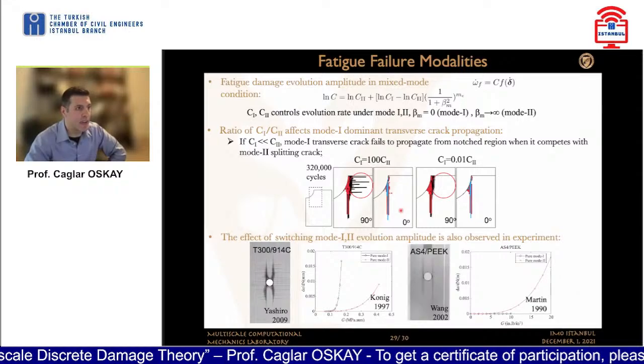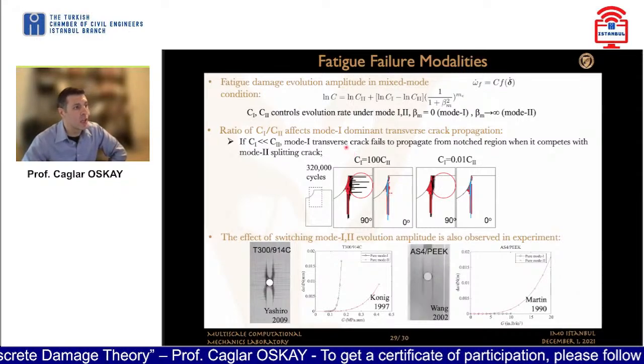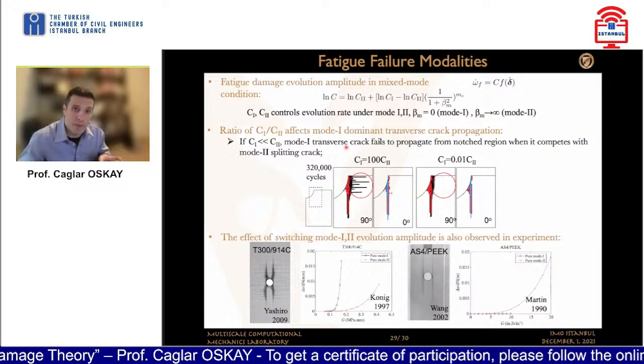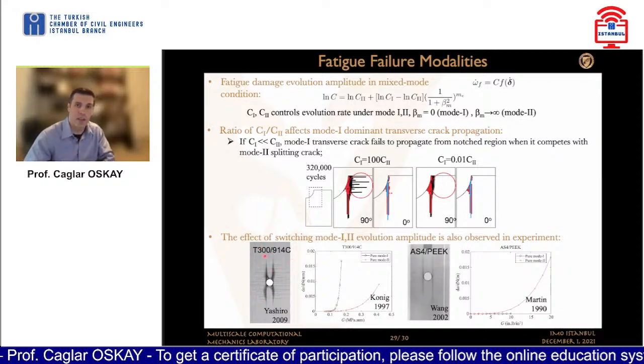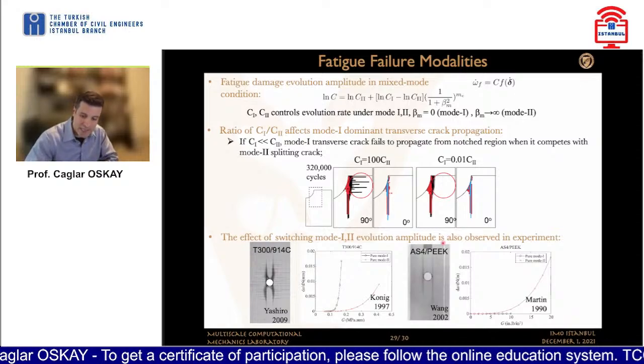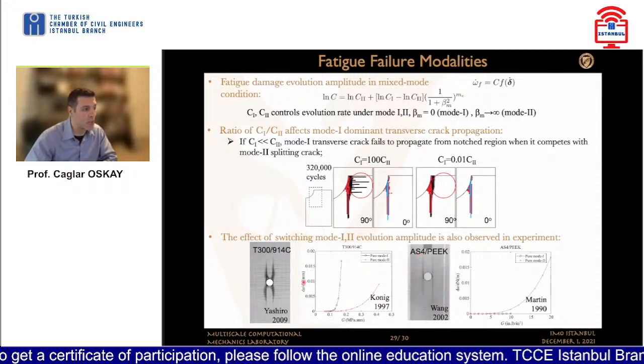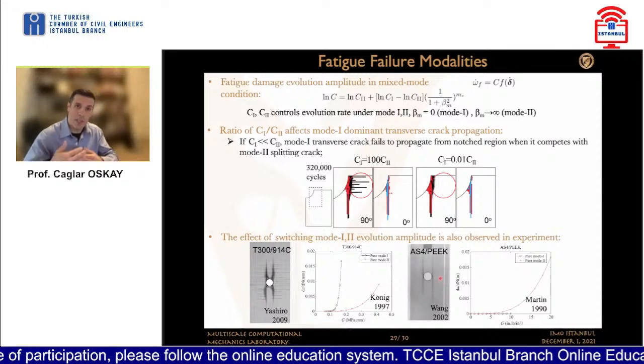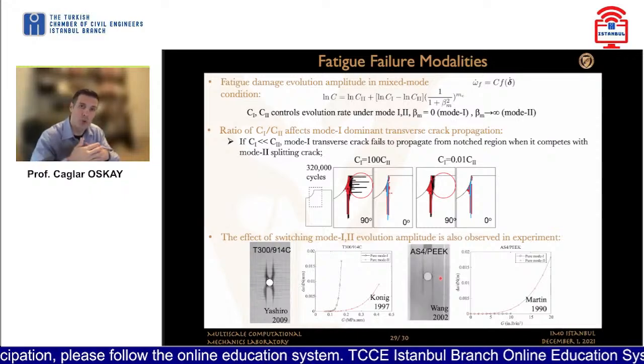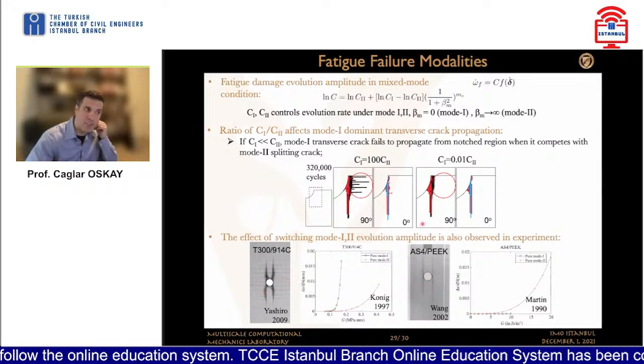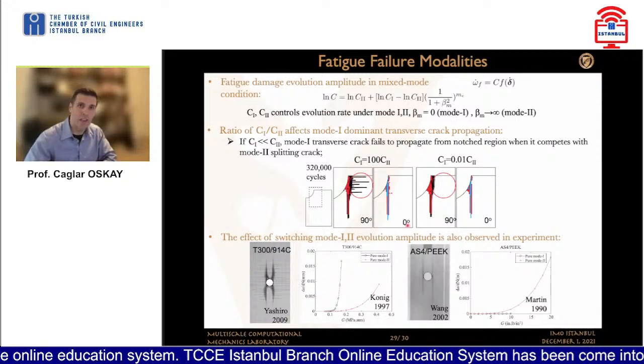In addition to that, we can also use this approach for different types of materials. Here we are comparing the behavior of a thermoset composite, T300 914C, to a thermoplastic composite, and they behave very differently. For example, as you can see here, in the thermoplastic composite you don't see the 90-degree matrix cracks that occur and propagate. That's because of the mode 2 fracture toughness of thermoplastic composites being bigger than the mode 1 fracture toughness, which can be modeled directly with the type of multiscale approaches that we're proposing.